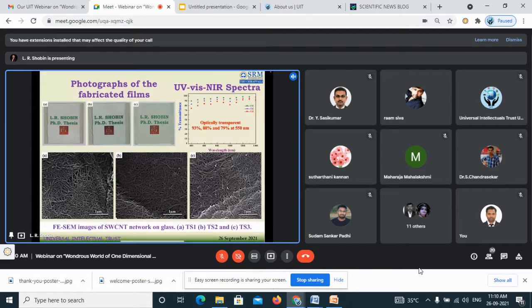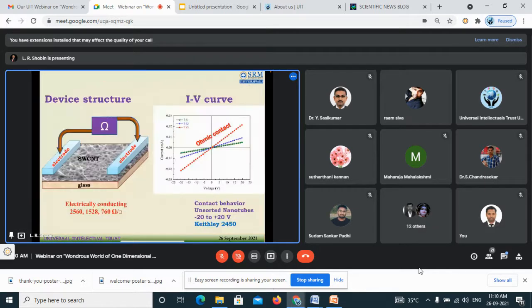If seen through the microscope, what you will see is a network of these carbon nanotubes. So you cannot see any individual nanotubes. They are all bundled together, bundled in nature, and they are forming a web-like structure over this substrate. These are all the SEM images of these web-like structures on the surface of the glass substrate. Okay. So far the films are good.